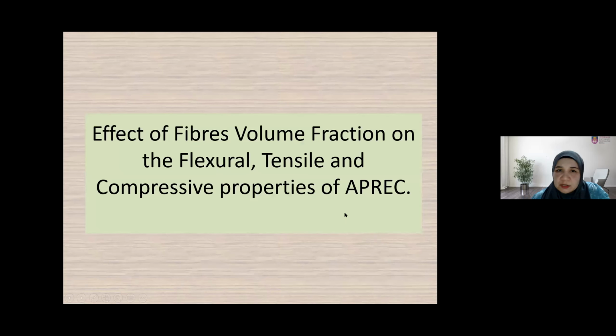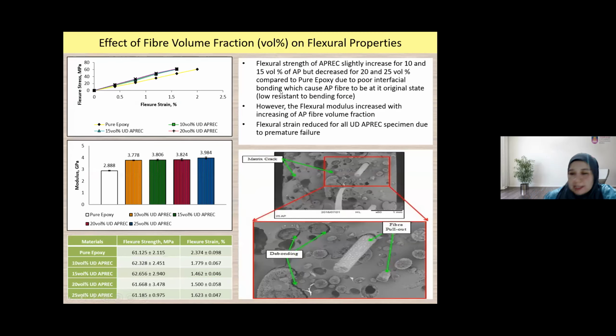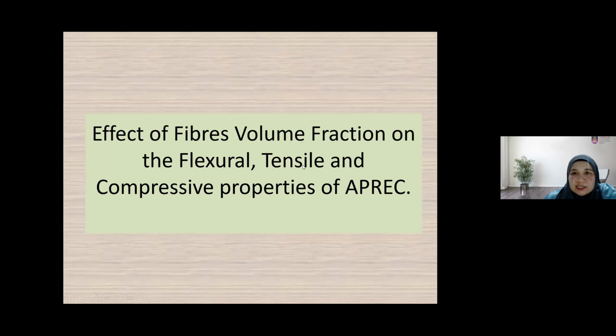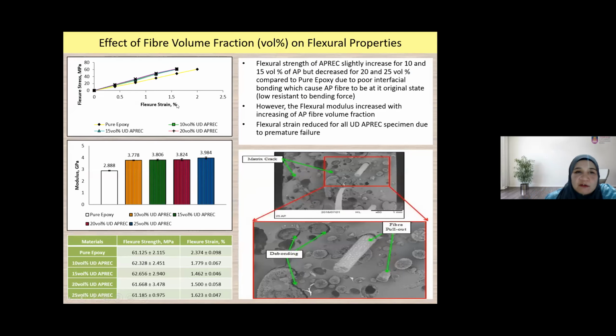Okay, so effect of fiber volume fraction on flexural. We concentrate on flexural and tensile properties of the composite. As we can see here, when we compare to the pure epoxy polymer, the modulus is about 2.88. If we put Arenga Pinnata in the epoxy, the modulus increases to almost 4 GPa with 25 volume% unidirectional Arenga Pinnata. In the epoxy, the modulus increases from 2.88 to 3.98.